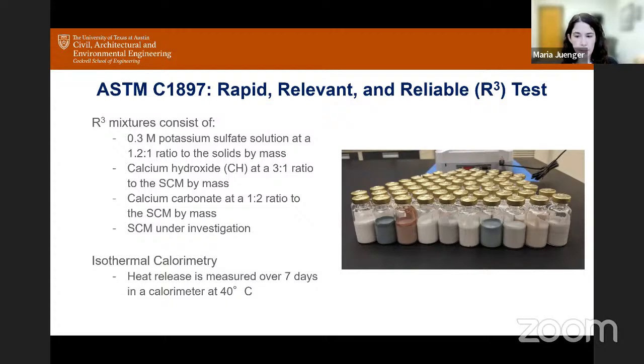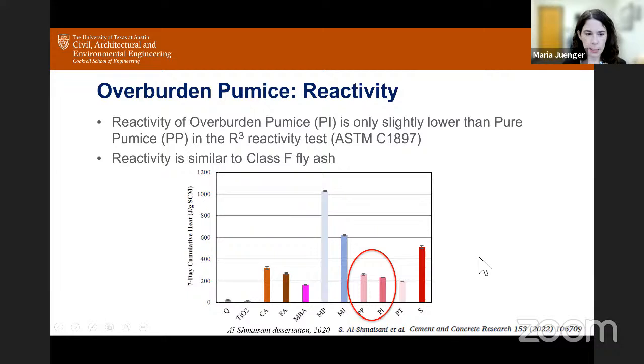As I mentioned, Jason Weiss's Pozzolanic reactivity test is a very similar test, but at a different solution composition and a higher temperature. So there's a couple of tests like this that are available out there. And so when you run this test, you get, in this particular case, the heat released, the 7-day cumulative heat in joules per gram of SCM that was run in that calorimeter for 7 days at 40 degrees C. When you run this test, you get different values. The higher the value, the higher the reactivity.